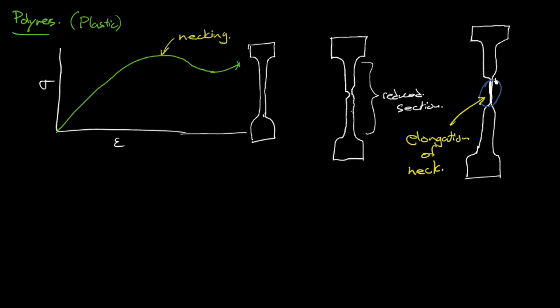The other thing that's neat to note here is that once the elongation occurs here in the middle, the polymer is getting stronger in that region that I've highlighted in white there. Or actually what I could do is I could make it, just for kicks, I'll make it blue, okay? And I'll say, look, the polymer is stronger there. And the stress is higher just on either side of it. Why? Because the cross-sectional area has decreased, and the polymer hasn't yet got as strong as it is in this little middle section. So we need to do is, okay, we understand that the polymer has gotten stronger, and it's gotten stronger significantly. So what we need to do is we need to understand how a polymer gets so strong during this plastic deformation in the neck.